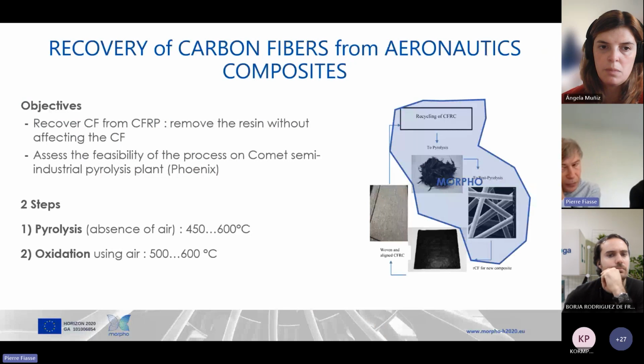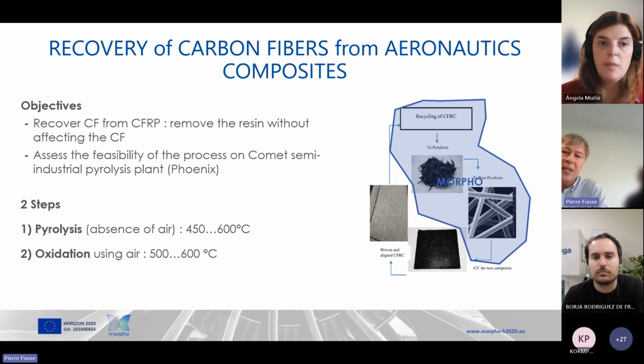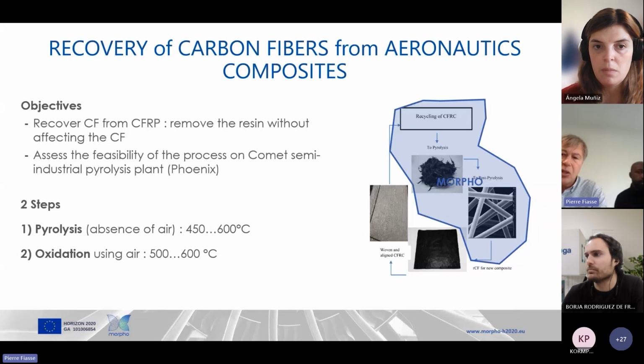Okay, so now I come to the Morpho project and our role in this project, and it was to recover carbon fibers from aeronautic composites. So the idea is to remove the resin without affecting the carbon fiber and assess the feasibility of the process. You see a picture here from a scientific paper where you have different steps. You have the pyrolysis step. Pyrolysis is a process to heat the material at high temperature without oxygen. This process enables to remove the resin from the composite, but there is still some resin on the fiber. And the next step is the oxidation to remove this resin and to obtain carbon fiber without resin.